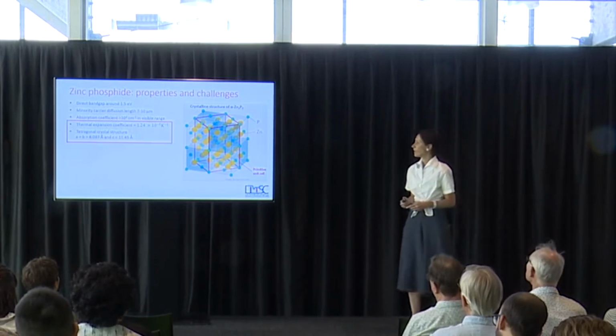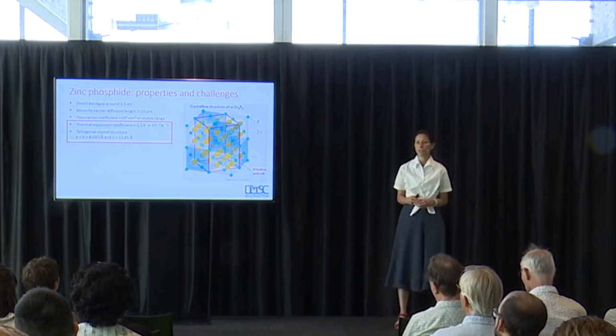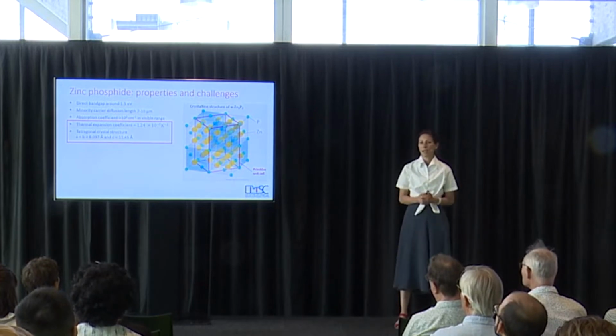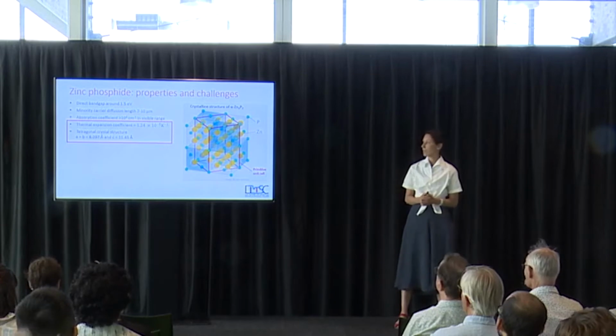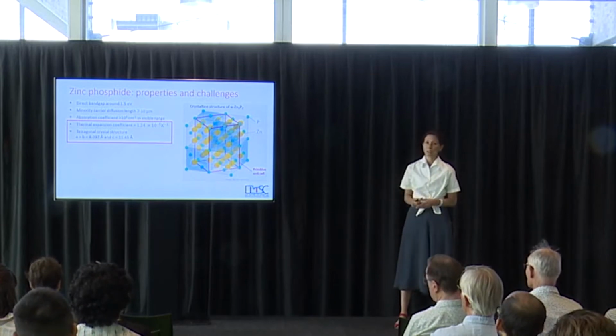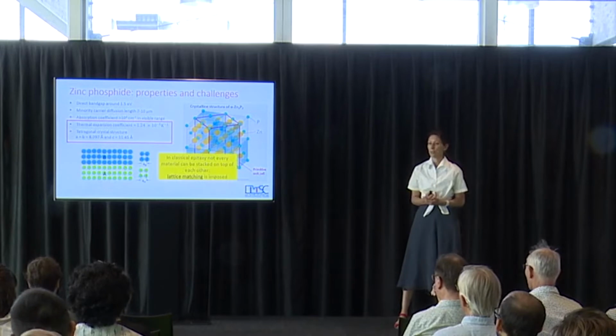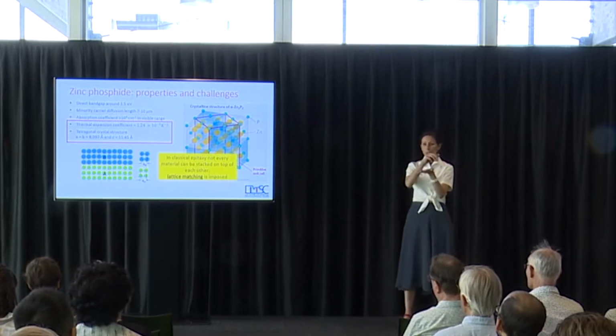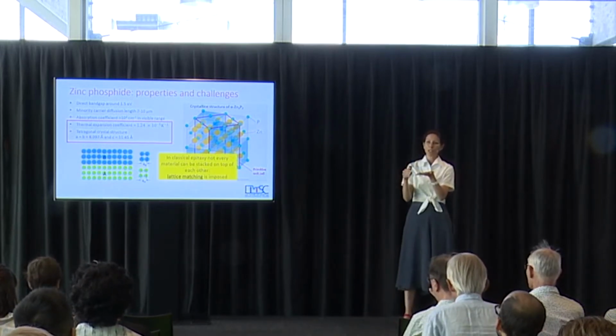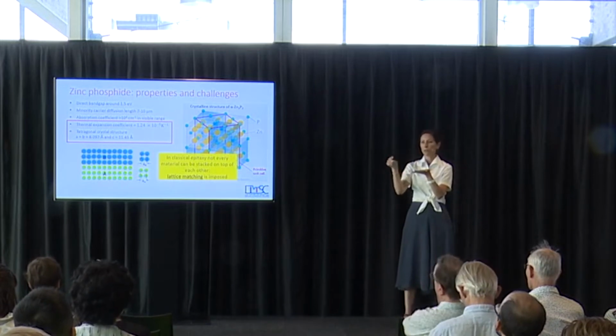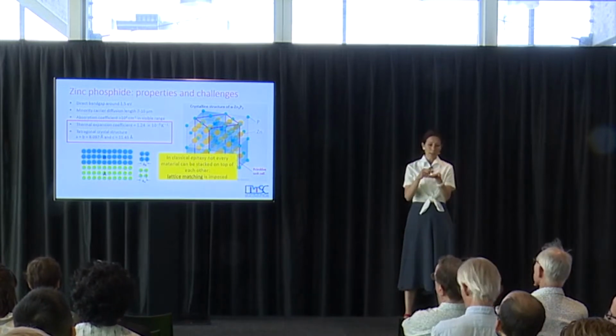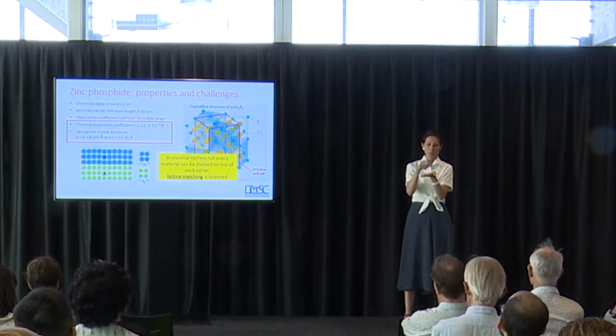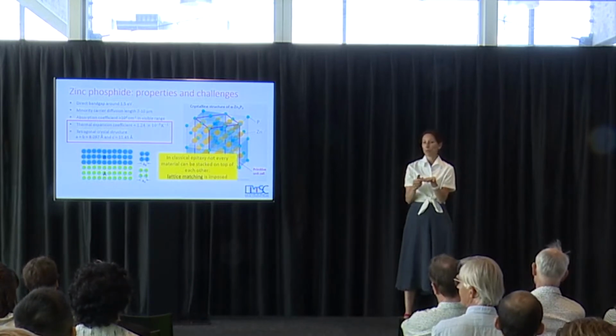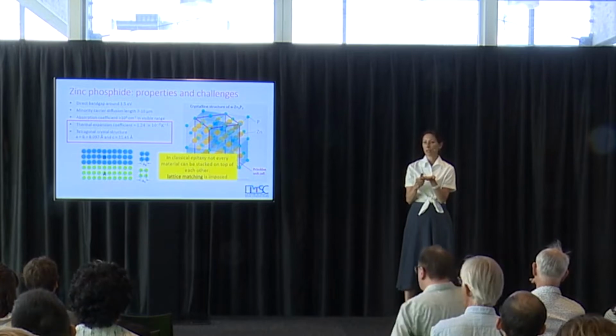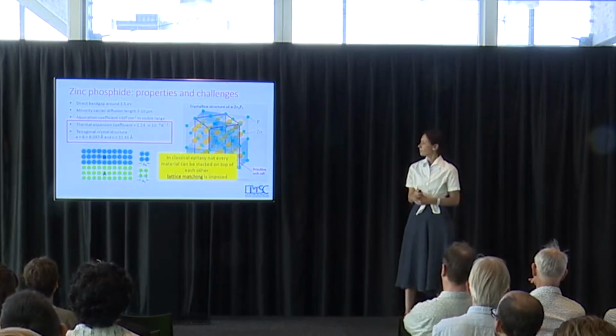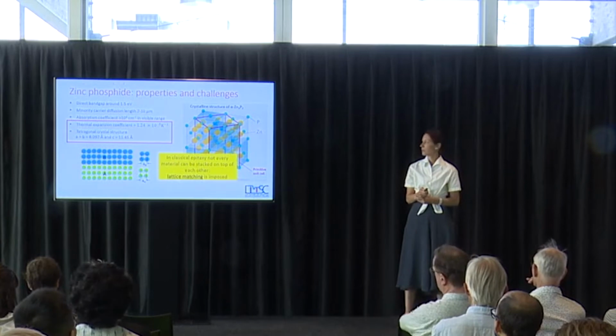The challenges are that the thermal expansion coefficient is not matched to any substrate, and there is no commercial substrate that can match this. So it means that if you want to grow high quality material, typically we order the materials on top of each other on a substrate, and the materials that you put follow the same order. And if you don't have any substrate that the atoms can follow the order of, then it's a problem, because it means you will have a hard time making crystalline material. And I will tell you today how we go around this.